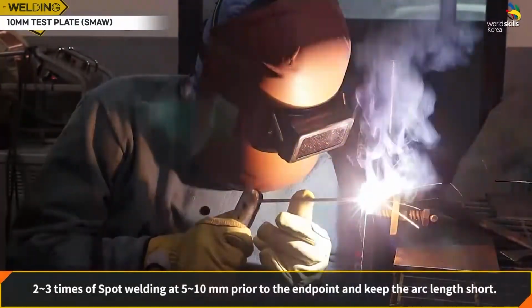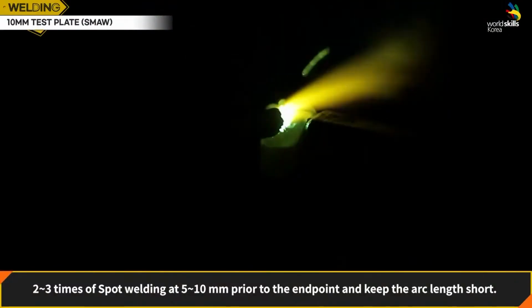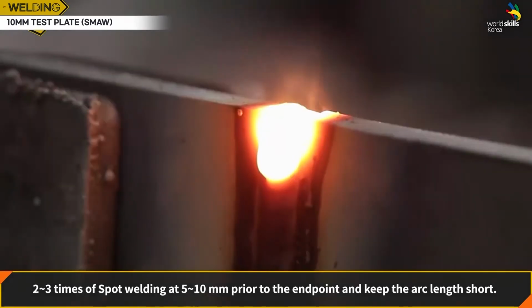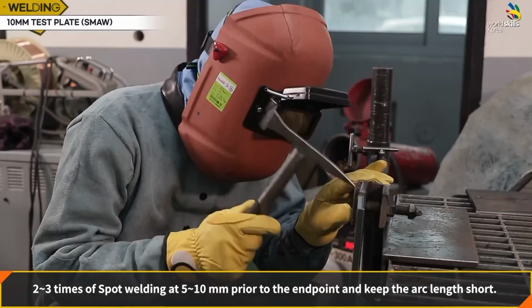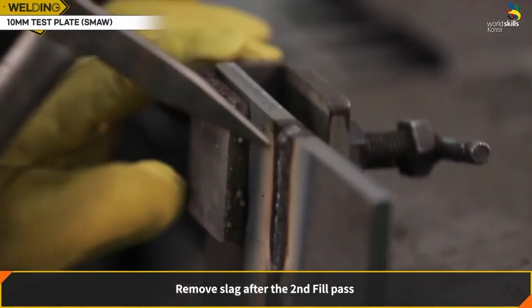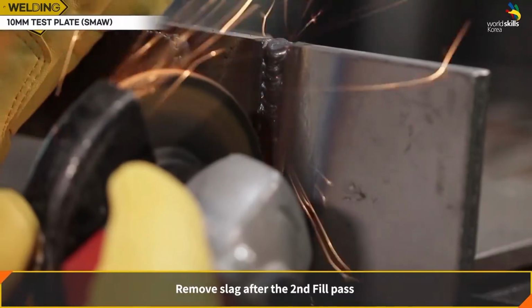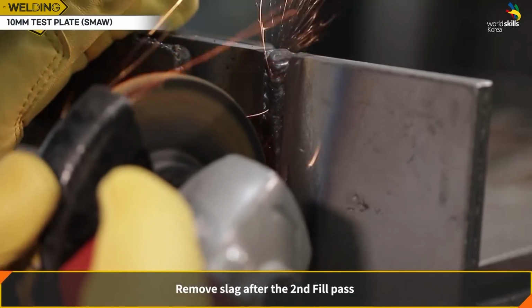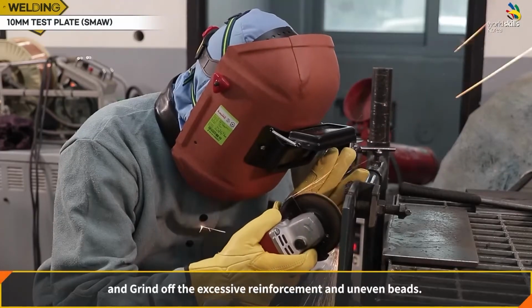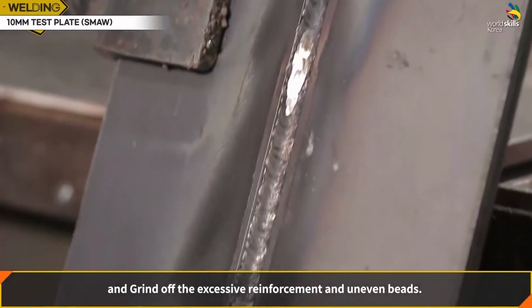Make 2 to 3 spot welds at 5 to 10 millimeters prior to the end point and keep the arc length short. Remove slag after the second fill pass and grind off the excessive reinforcement and uneven beads.